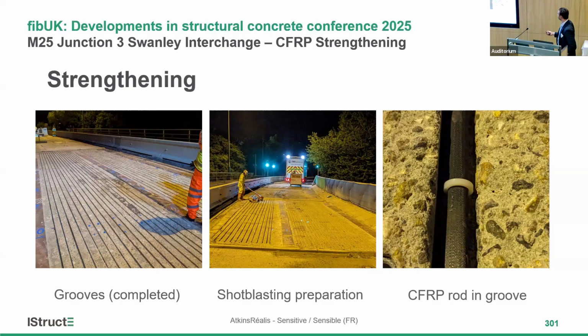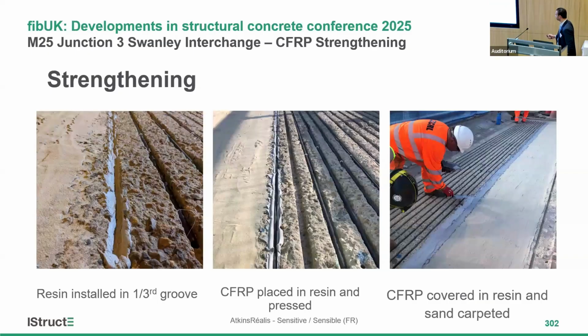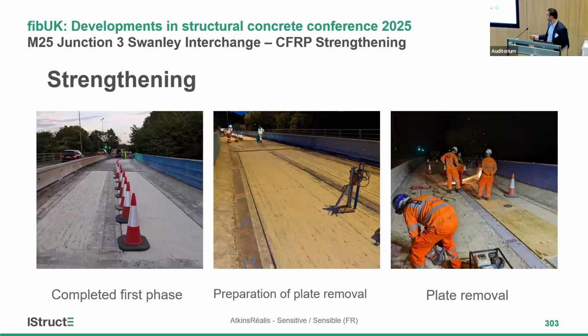Just to check to see if the CFRP rod fits into the groove. And then you install 1/3 of the groove with the resin. You install the bar, and then you fill it up along with the sand carpet. This is the completed first phase. And then we give a gap of 24 hours overnight, so the resin sets in.